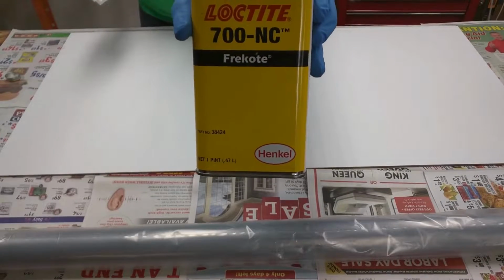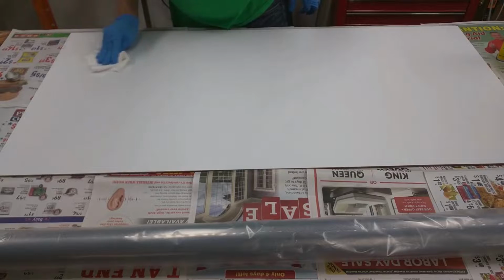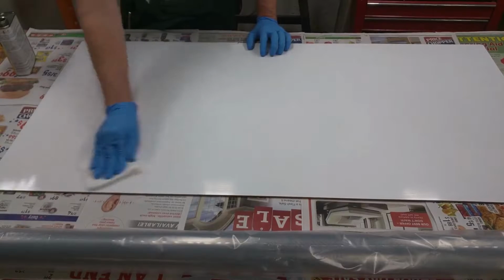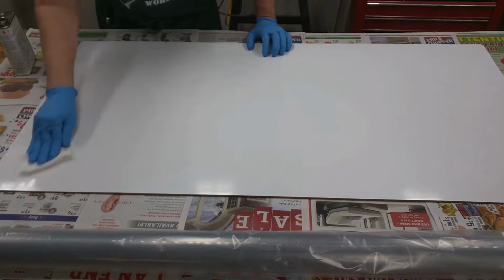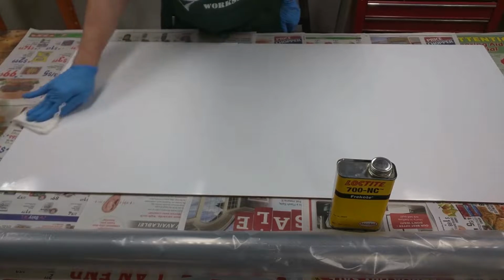What I'm going to be using for the release agent is different than last time also. Last time we used wax with 3 coats of PVA, polyvinyl alcohol, on top of it. This time we're going to be using Loctite 700 NC Frekote. This appears to be a fairly common release agent, so we're going to give it a try. I'm applying this Frekote in 3 coatings using a different wiping orientation for each coat. So on the first coat, I'm going left to right, wiping it down. On the second coat, I went fore and aft, away and then back toward me, back and forth. And then on the third coat, I went at a 45-degree angle.